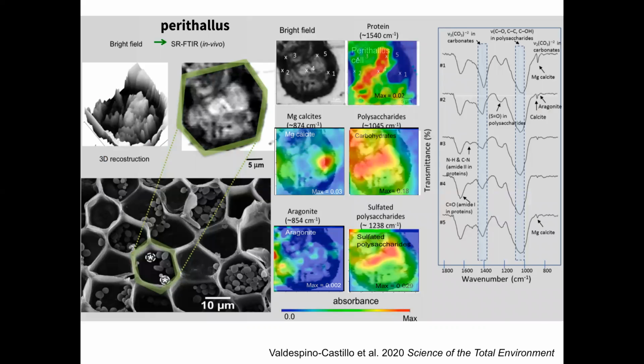And here to the left bottom, you can see this SEM micrograph of the perithallus hexagonal shaped cells. Some of these cells exhibit a content similar to spheres, as you can see. And on top, you can see the bright field microscopy of a single perithallus cell, which is more or less 20 microns in diameter. In the center, you can see synchrotron infrared chemical information. The heat maps represent spatially resolved infrared signals based on a single perithallus cell. Under the bright field image of the cell, you can see how we were able to detect a spatial segregation of 2 minerals, magnesium calcite and aragonite, at a scale as small as tens of microns. To the right, you can see the protein signals and the polysaccharide signals that occupy all the cell content.